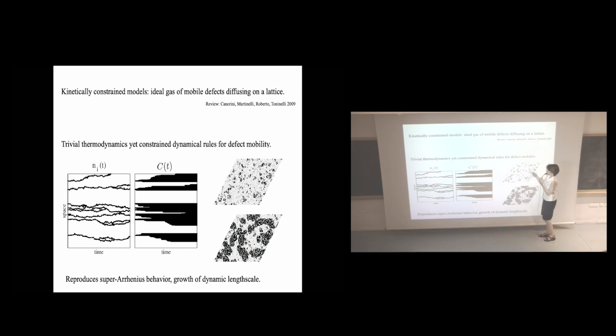Here, this is the same in 2D. So you would have point defects, and then they can move in time. You imagine time going down below. And if you look at the trace, then you get these domains, which are quite large. So you can get a large correlation length in the dynamics. But the statics here is completely irrelevant. Okay? So you can think about this picture for now. It's really just an increasing dynamic length coming from dynamics that is simply constrained.